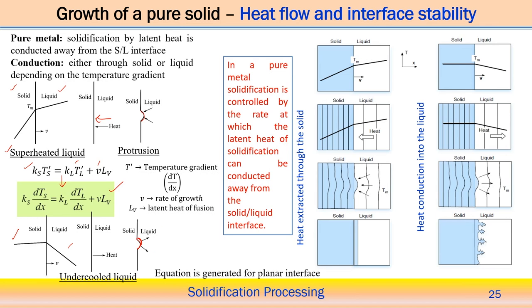Therefore, I can say that in a pure metal, solidification is actually controlled by the rate at which the latent heat of solidification can be conducted away from the solid liquid interface. It depends entirely on this: solidification is controlled by how the latent heat is extracted at the interface.